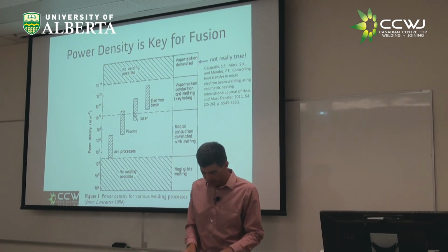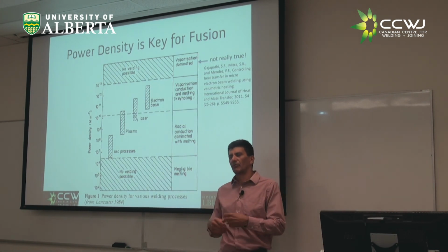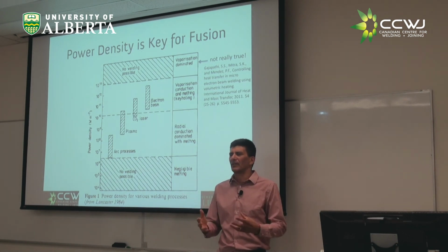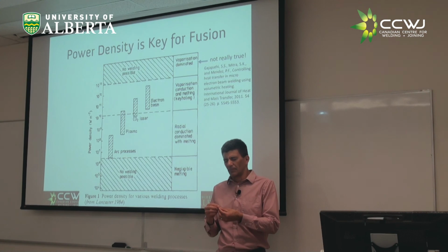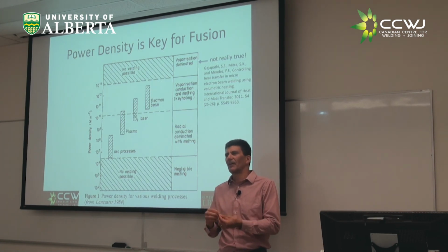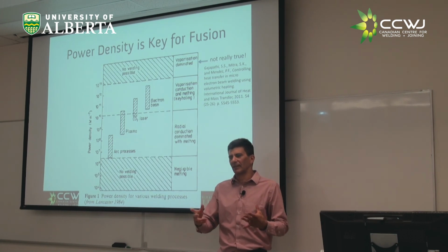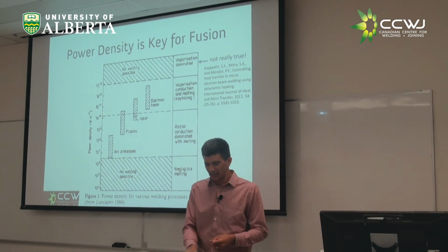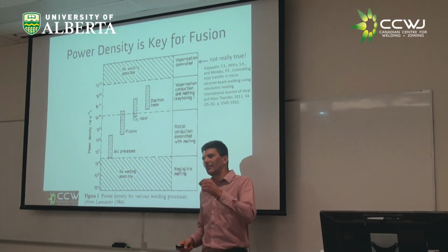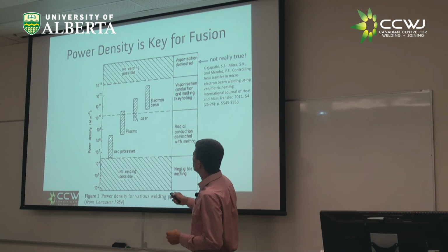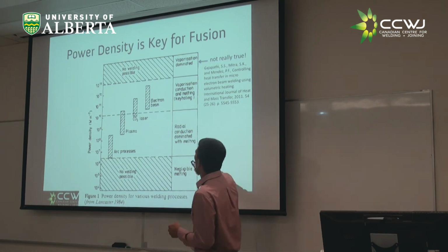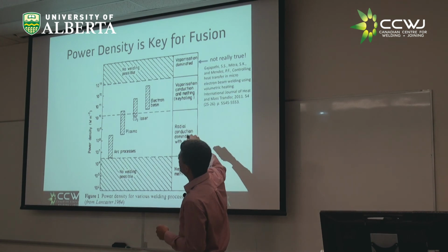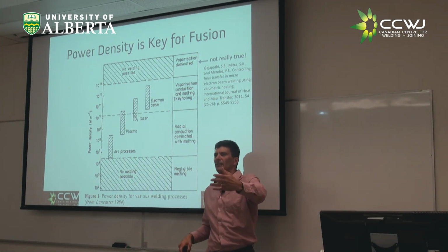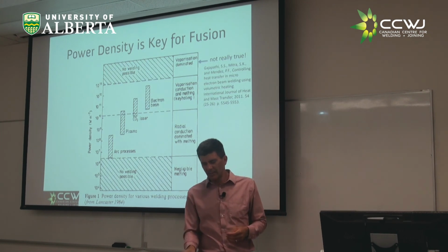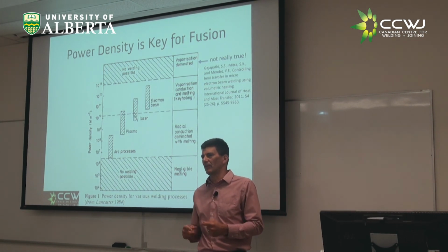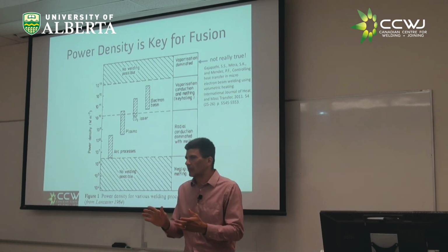And the reason fusion welding didn't exist until around 100 years ago was that people had no way of getting thermal energy as concentrated as in an arc. But then with the discovery of electricity, people started to play and figured out, oh, look at this big spark, how hot it is. Then, without really knowing what they were doing, they started to move up here in power density. Now, here it says that there is no welding possible when you have too high heat intensity, because you're not melting, you're just cutting, ablating it. There is some truth to that.